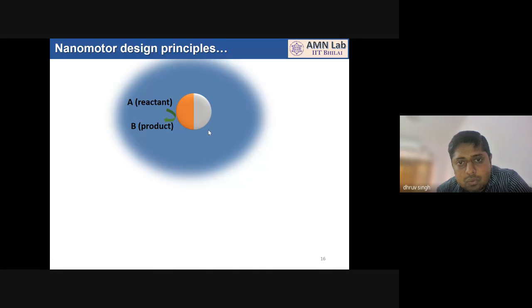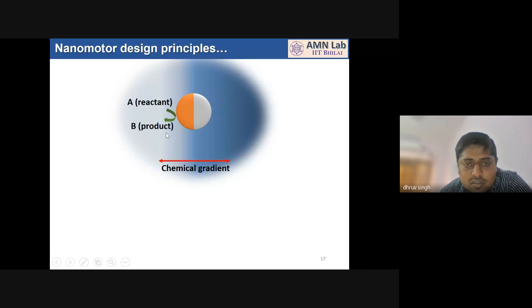So now assume you have a Janus particle, where suppose this orange color material is chemically active and the gray color material is inert, or some passive material, and you put it in a chemical medium, for example peroxide. Sometimes even water is a chemical in chemistry, so there could be several chemicals. You put it in some chemical medium such that this material can react with or decompose this chemical. Then what will happen? The chemical activity is happening only on one side of the particle, because the other side is inert. So it will make a chemical gradient around the Janus particle.